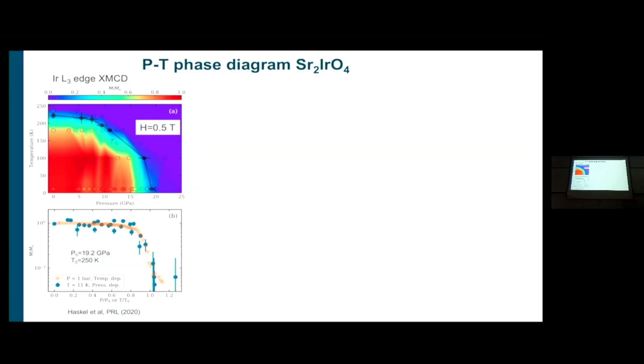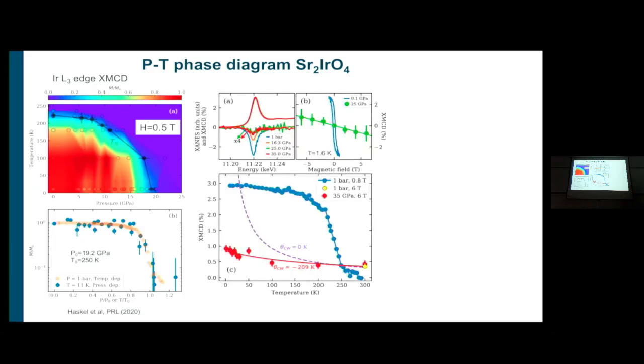So we can build a pressure-temperature phase diagram, and as a function of temperature at zero pressure, it goes paramagnetic at 200 and something Kelvin, and as a function of pressure at around 20 GPa, it goes paramagnetic. And this is a second order transition that you can scale, and you can find an order parameter. It looks like it becomes a paramagnet at low temperature. So if you go at low temperature, which is the experiments we did, the magnetic order goes away, becomes a paramagnet, and you can measure the temperature dependence of this.